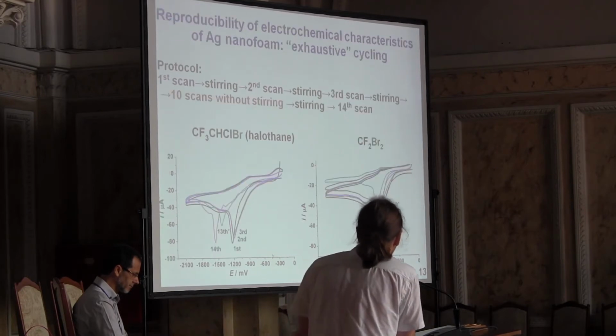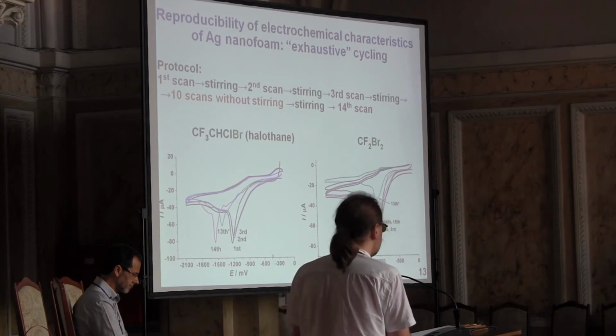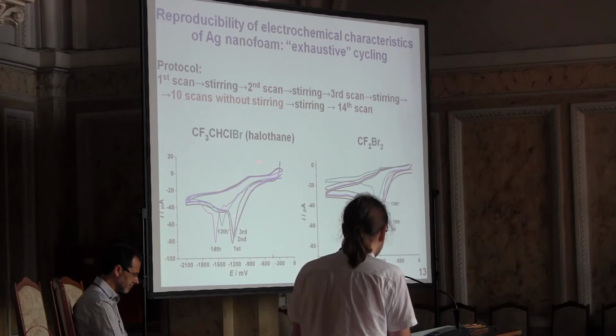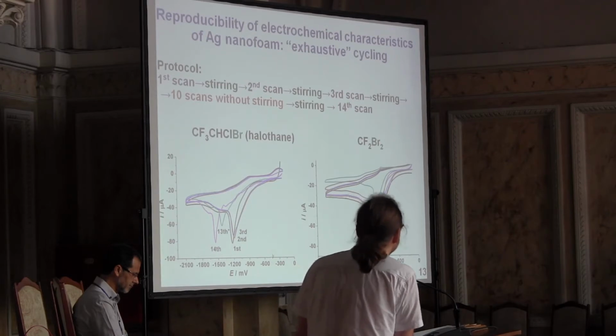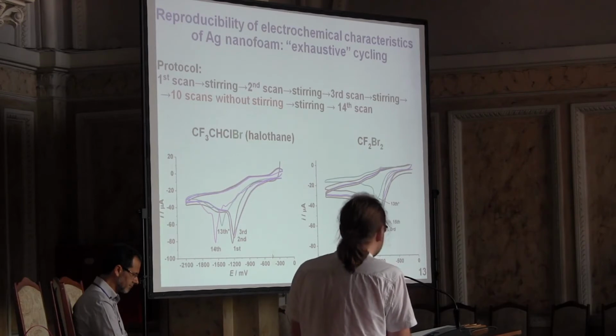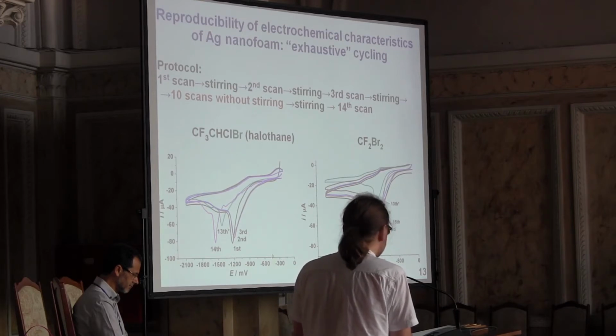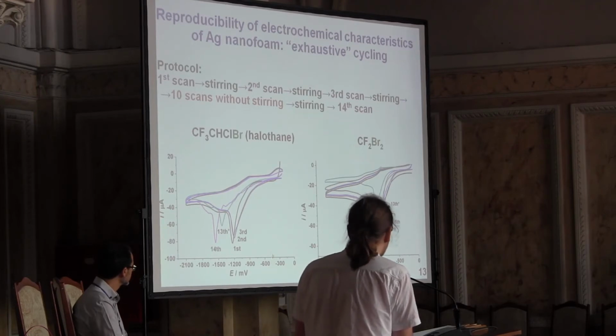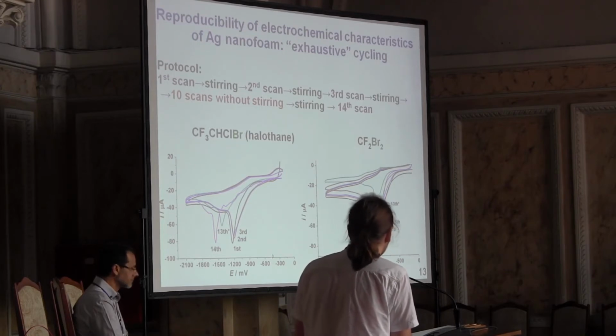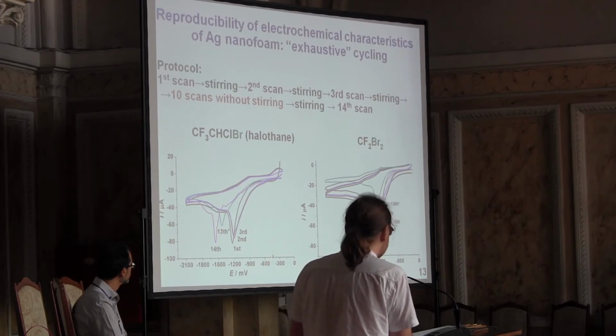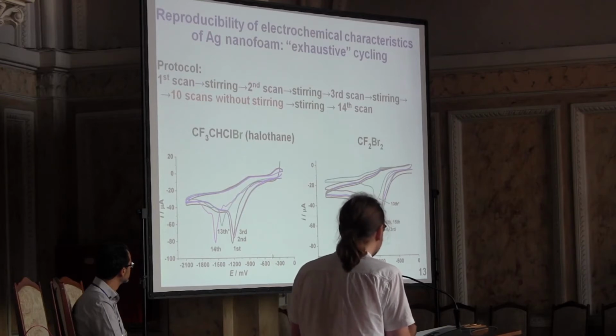If we subject the coating to the continuous scanning without stirring, we observe irreversible degradation of electrocatalytic performance in case of halothane, or reversible in case of dibromodifluoromethane. Such difference can be explained by possible dissolution of electrocatalytically active sites of the silver nanofoam by the products of reduction of halothane. First of all, substituted olefins that can form in this process and can form soluble complexes with silver.